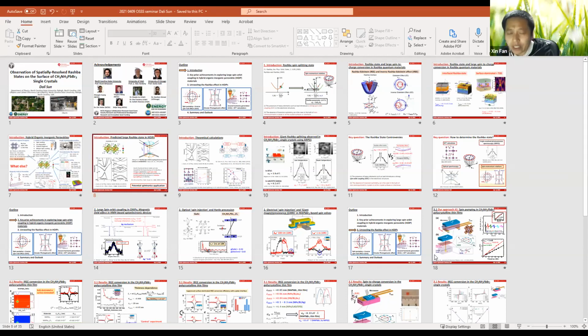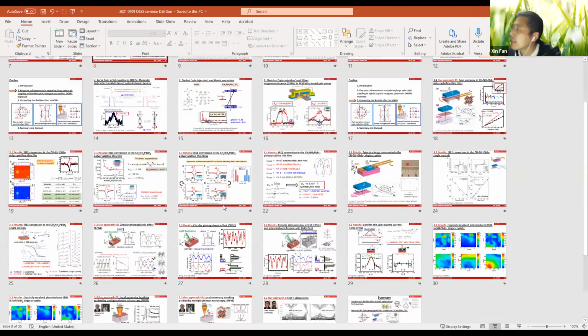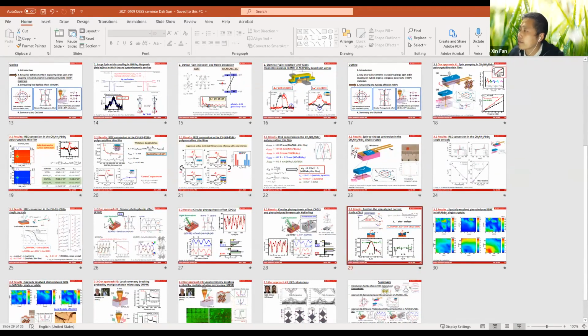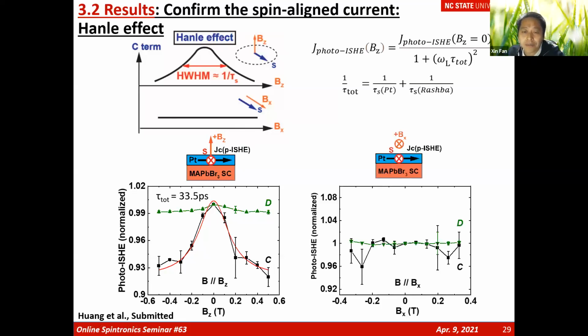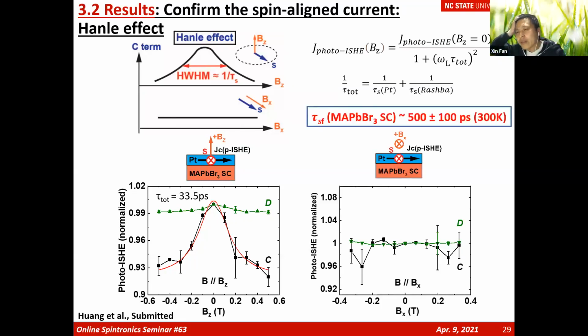So I believe it was slide 29 when you did the Hanle effect in the case of optical pumping, this inverse spin-Hall effect. Yes. Can you just remind me, the Hanle effect, this is still the Rashba effect, right? Is the spin generated at the interface, or is it generated in the bulk of the perovskite material? Basically, is the Hanle effect related to spin dephasing as it propagates? Where does that take place? Is it taking place in the platinum, or in the perovskite material?